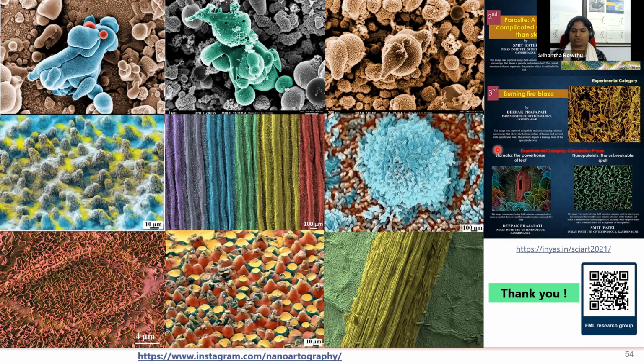And finally, if you check the particle sizes with the laser, you are going to get a single distribution curve, but not the double distribution. If you get a bimodal curve, it means that the agglomerates are still present. If you get a single distribution curve in the particle size analysis, then it means that most of the particles are nicely deagglomerated. Does that answer your question, Shivprasad?